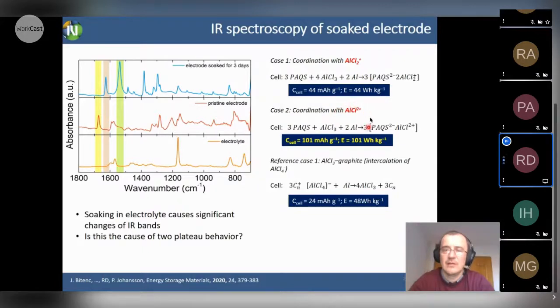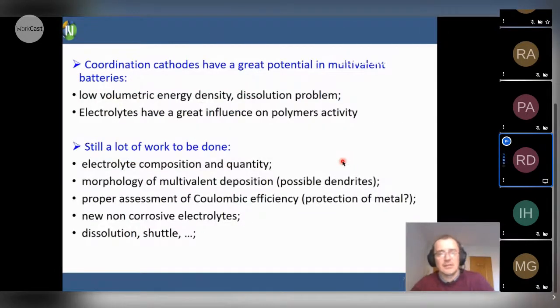Now moving to divalent coordination, this increases, of course, but still it's quite low, and so we need to improve this. But it's twice the maximum that can be obtained with graphite. So those numbers show that there is a possibility to have something really attractive, but of course we need to come with some better cathodes and maybe also an electrolyte, which will enable us at least a divalent aluminum complex, if not trivalent, pure aluminum. And that brings me to the end.